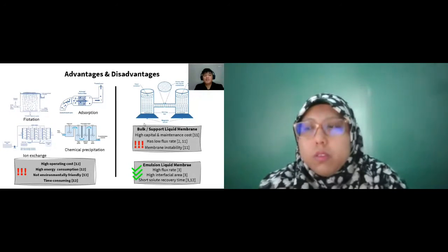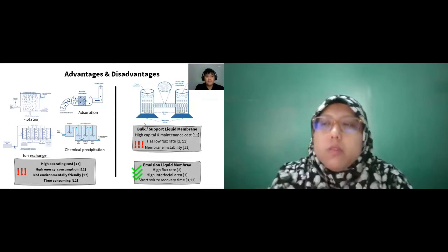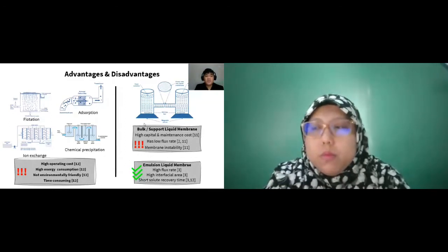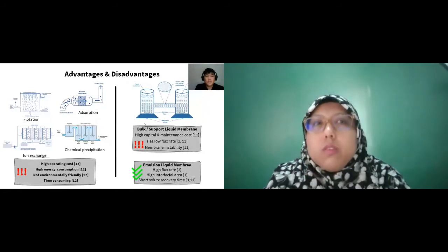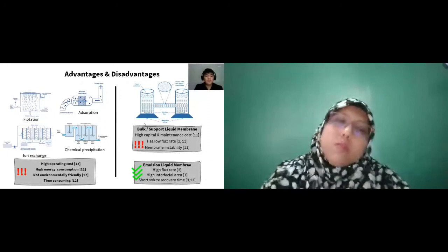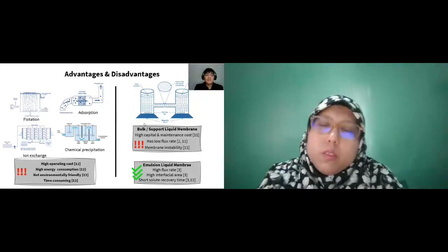Emulsion liquid membrane has been proven to be the best liquid membrane process to extract heavy metals. It has high flux rate due to the high interfacial area. The interfacial area is reported to be approximately 1,000 to 3,000 meters square per meter cube, compared to the bulk liquid membrane and the supported liquid membrane. It is 40% less costly than solvent extraction, and solute can be extracted in a short time. Emulsion liquid membrane has been applied in separation of organic acid, purification of antibiotics, enzyme catalysis reaction, and blood acidification.